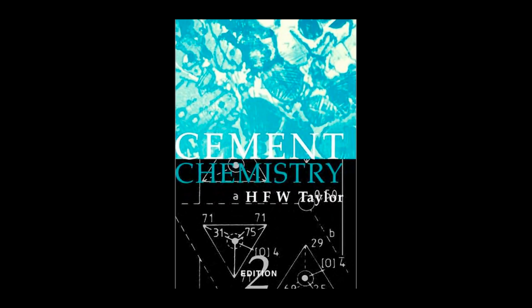And what are the chemical characteristics of this liquid? It is extremely basic and highly fluxing. Data from phase equilibrium studies show that the liquid in equilibrium with the silicates at 1400 degrees is very high in CaO, often 54 to 57%, and it's also rich in Al2O3, which can range from 15 to over 30%. Its high reactivity is what allows the system to achieve its final composition so quickly. And the dynamics of this liquid phase also dictate the size of the alite crystals, which in turn dictates the speed of strength gain. Yes.